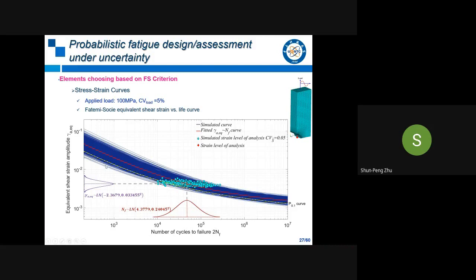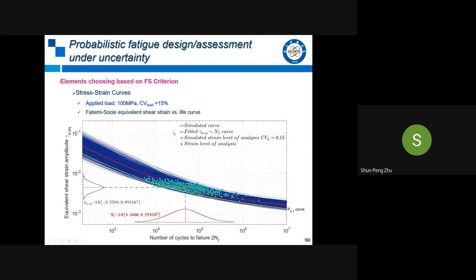And in these curves, the red curve is the median. Normally, this one is the median. Also, in the handbook, this is the 50% failure probability design curve. And here we choose the strain level for this analysis. Then we list another with the same load but a larger load variation. We can note from the results that the strain amplitude also shows a larger scatter, and the life also has a larger distribution. And these are the two results.